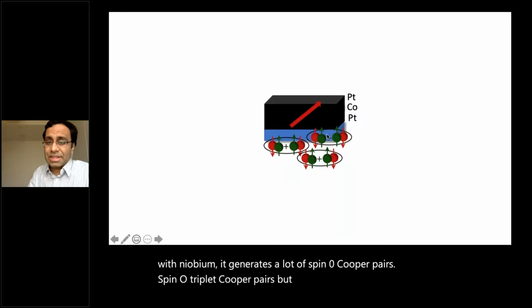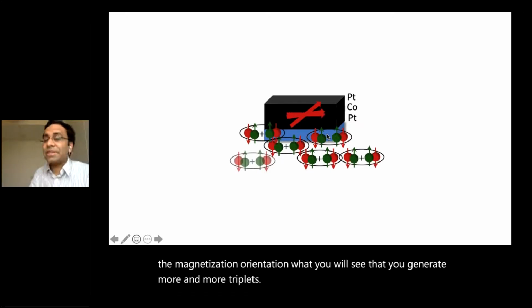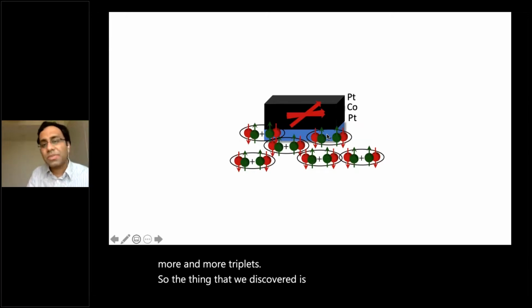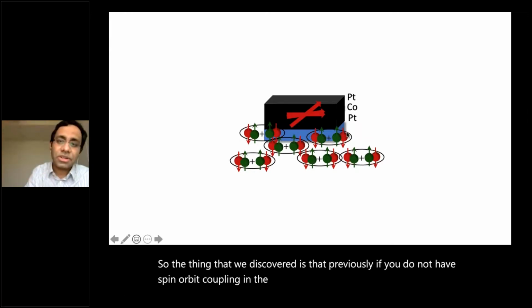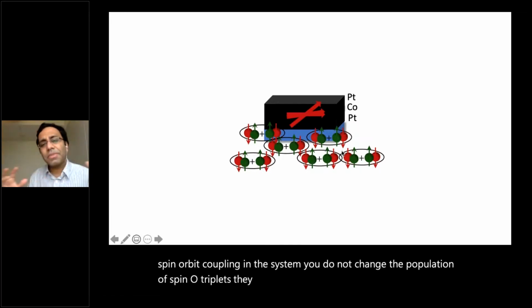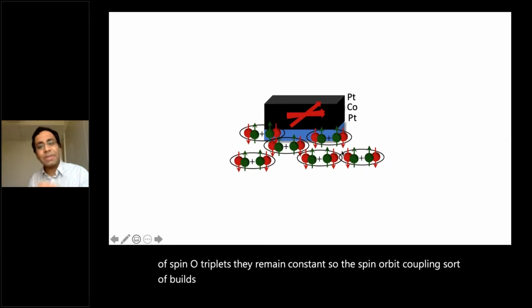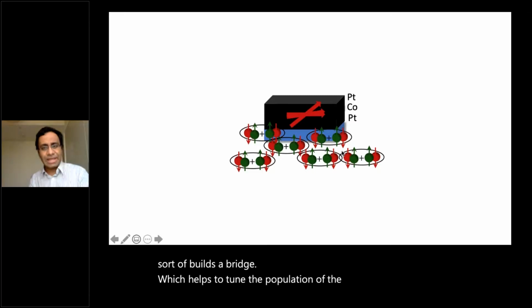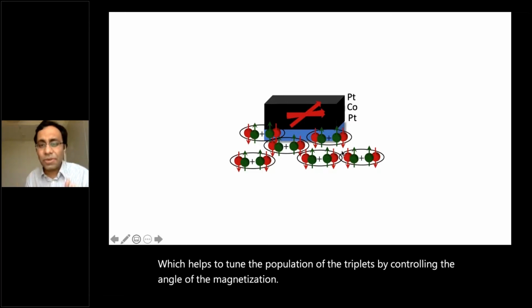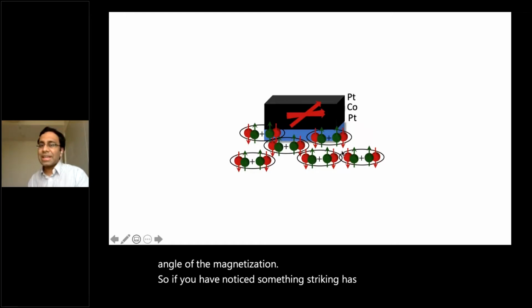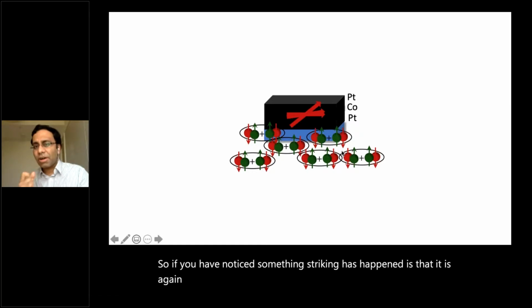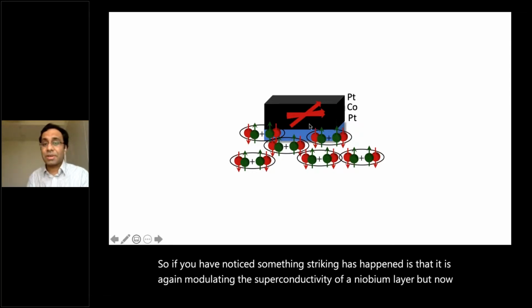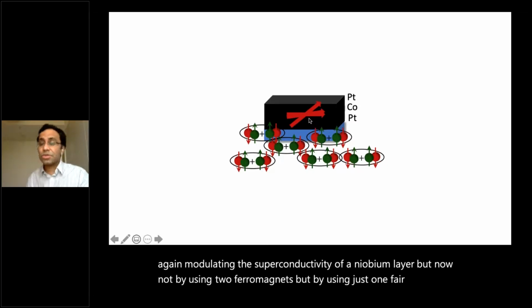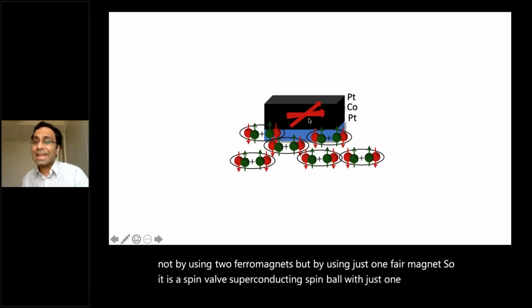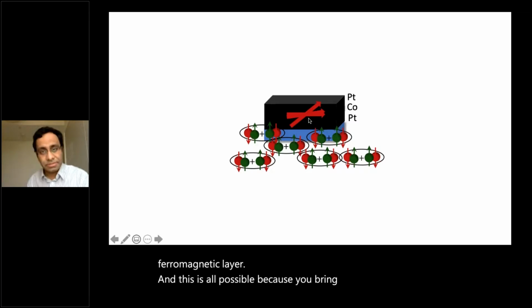But the key fact here is that if you change the magnetization orientation, you generate more and more triplets. So the thing that we discovered is that previously, if you do not have spin orbit coupling in the system, you do not change the population of spin zero triplets. They remain constant. So the spin orbit coupling sort of builds a bridge which helps to tune the population of the triplets by controlling the angle of the magnetization. If you have noticed, something striking has happened: it is again modulating the superconductivity of a niobium layer, but now not by using two ferromagnets, but by using just one ferromagnet. So it is a spin valve, a superconducting spin valve with just one ferromagnetic layer. And this was all possible because you bring in spin orbit coupling into the picture.